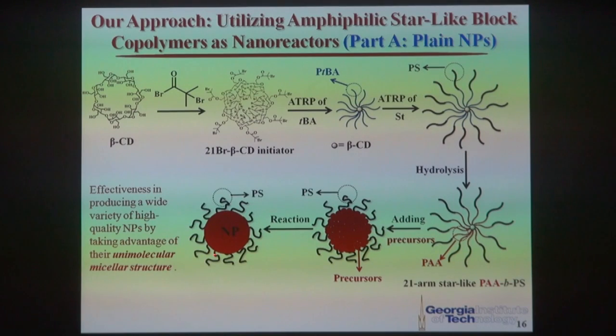So now the size of the nanoparticle is dictated by the length of the polymer chain, PAA, right? That is the length of PAA to start with. So this can be well controlled by atom transfer radical polymerization because it is a living polymerization technique. Now, the solubility of the resulting nanoparticle: you look at here, it is capped by polystyrene. So that renders the resulting nanoparticle soluble in a large variety of non-polar solvents.